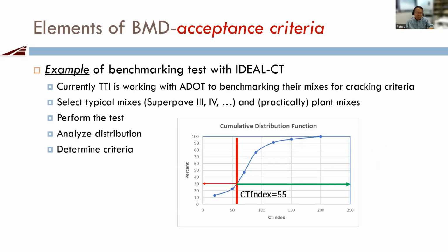And then benchmarking. Currently TTI is working with Arizona DOT to benchmark their mixes. So you just choose the typical mixes, perform the test, and analyze the distribution. For example, this is a distribution for the CT index, a cumulative distribution. If I want 70% of my mixes passing, that's how we come up with the criteria: CT index is 55. If you want 50% passing, you probably talk about 65 or 70 here.